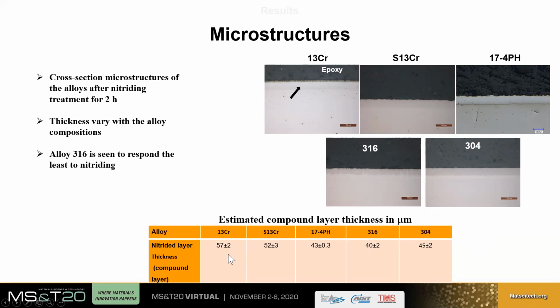So the thickness of the nitride layer depends upon the time, temperature and alloy composition. In this particular study, time and temperature were kept constant, therefore alloy composition controls the thickness of the nitride layer. Alloys rich in nickel and molybdenum, such as 316 and 17-4 PH, have a thinner nitride layer compared to other materials. That could be due to high nickel and moly content, which does not allow nitrogen and carbon to diffuse into the lattice, whereas 13 chrome shows a relatively thicker nitride layer.